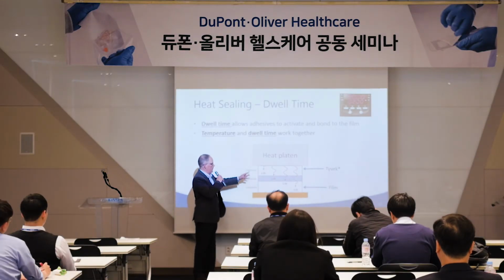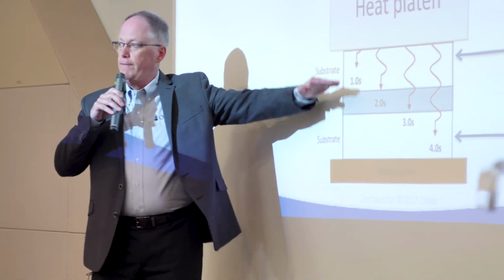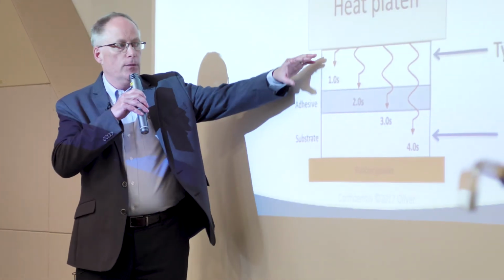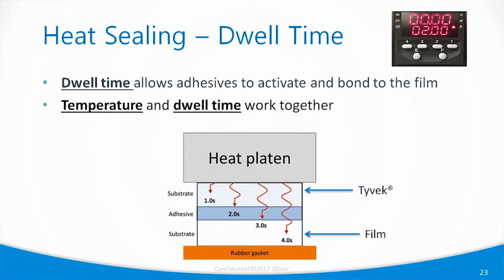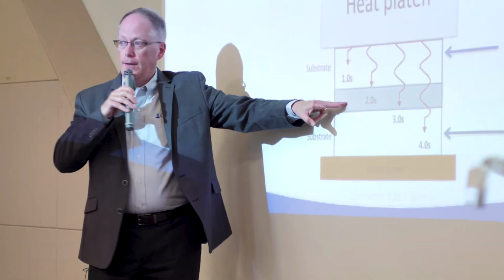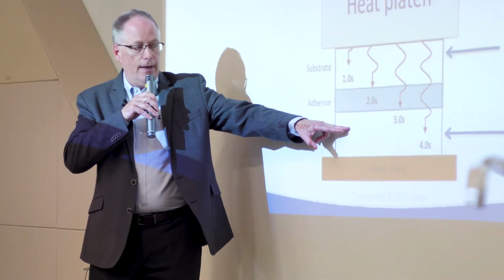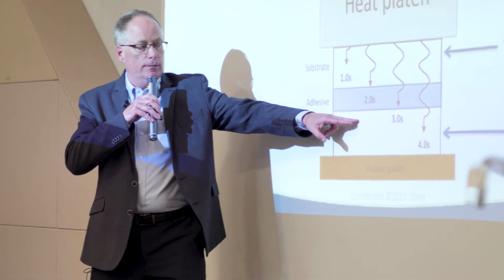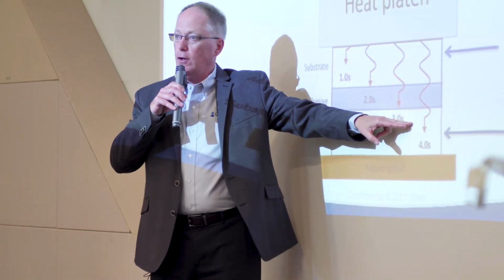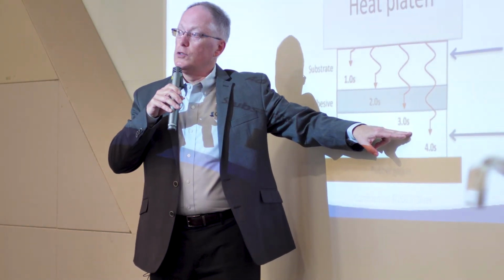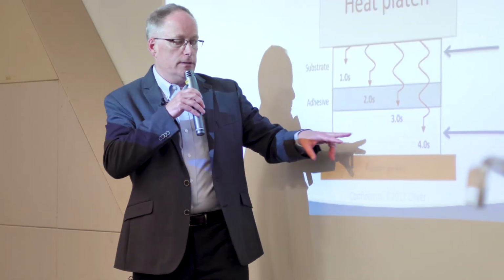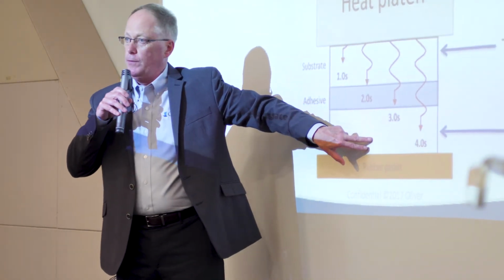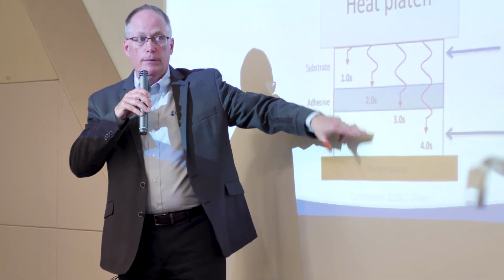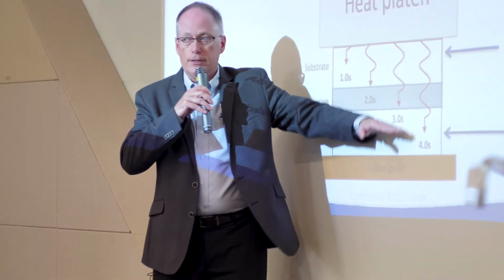So I was going to go over this, but I think you probably covered it. This is a good way to visualize in your sealing process. You need to have enough time to get through the Tyvek, get enough heat into the system to get the adhesive to activate and also bond to your film. So if you think about your sealing processes, depending on the thickness of the film that you're using, thicker films might require a longer dwell time to make this whole thing work.